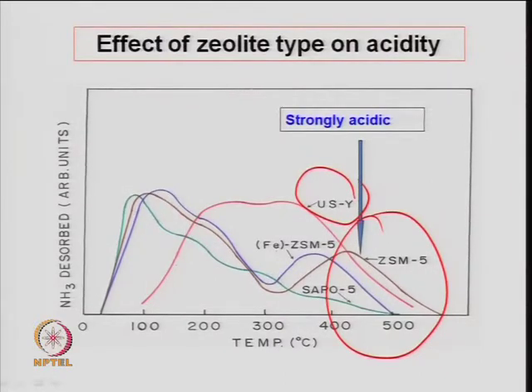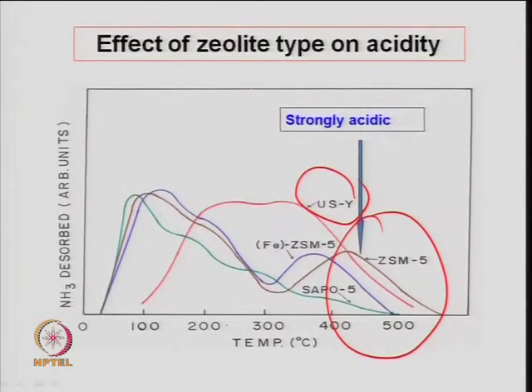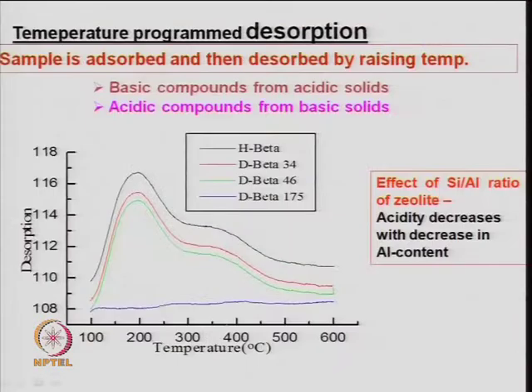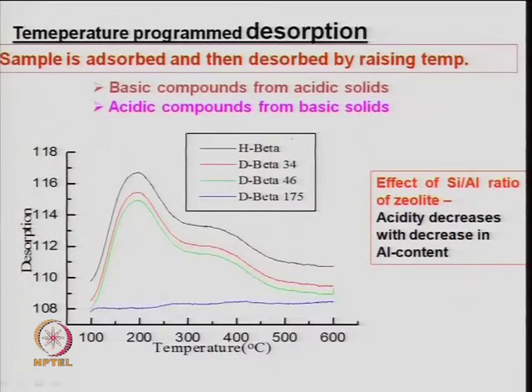Total concentration is the area under the curve; if you divide them into different temperature zones — say 200 to 400°C — you can get the milliequivalent of ammonia which has desorbed from the surface. A comparative study can be obtained: which catalyst has higher number of acid sites and which has higher strength of acid sites — both information can be provided by ammonia TPD.